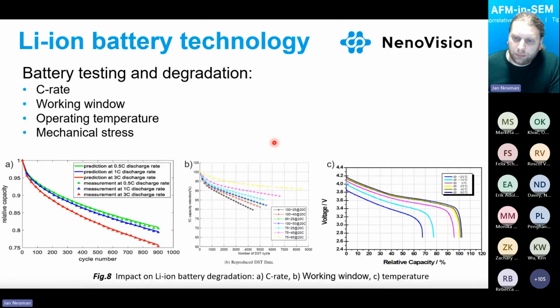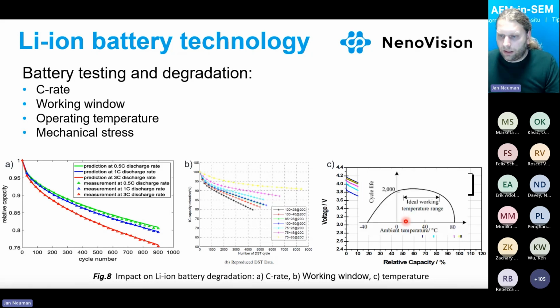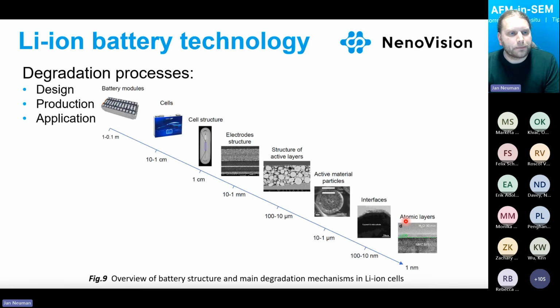As you can see in picture C, if we increase the temperature, usually capacity is higher. If we decrease the temperature, we increase internal resistance and the capacity goes down. And from the point of view of cycle life, if we increase the temperature, we usually decrease the cycle life of the batteries, and the same if we decrease the temperature. But in the case of low temperature, the battery is not as sensitive compared to higher temperatures.